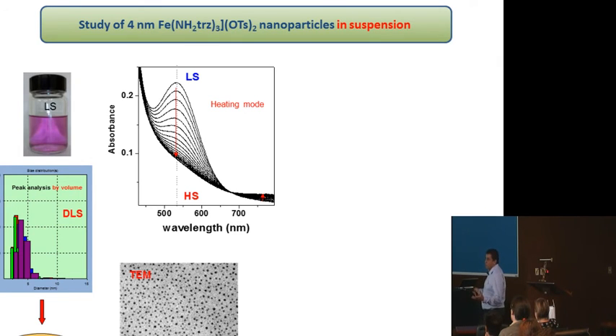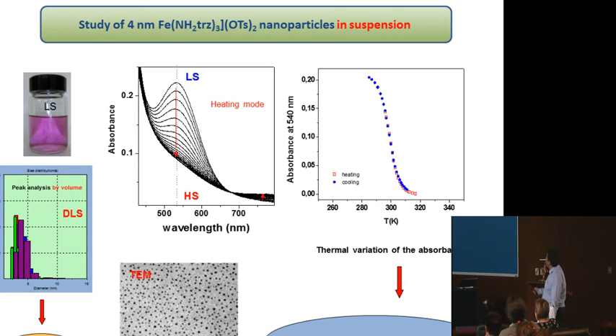So it's not powder, because if you have powder, you can have interaction between nanoparticles and aggregation effects. Using this solution, you are sure that you have a suspension of nanoparticles, so you remove the possible aggregation of the particles and its effect on the spin crossover property. Now if you look at the properties, here is the absorbance at 540 nanometers as a function of temperature. Using this absorbance measurement, we obtain the spin crossover properties. With these 4 nanometer particles, we maintain an abrupt transition, but we lose the hysteresis, because it's a very small nanoparticle.